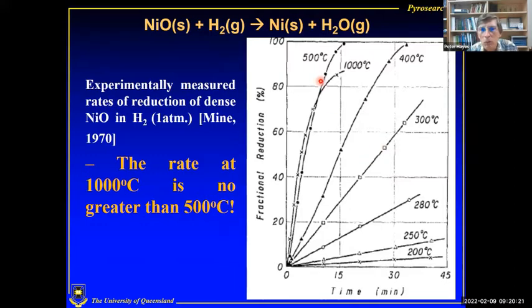And well, there's something strange happening here. We find that the rate at 500 is the same as 1000 degrees centigrade. So these guys have increased the temperature 500 degrees more with no benefit at all. That's not what we expect from the Arrhenius equation.